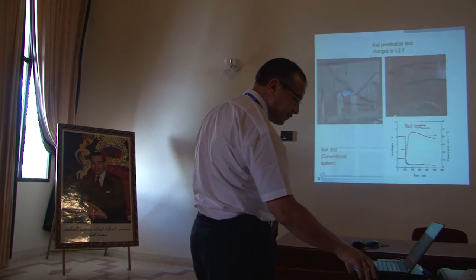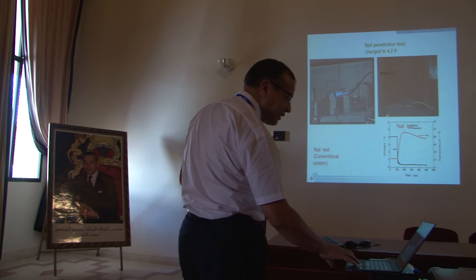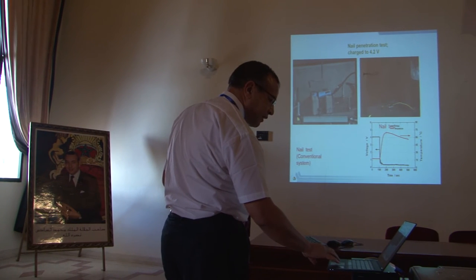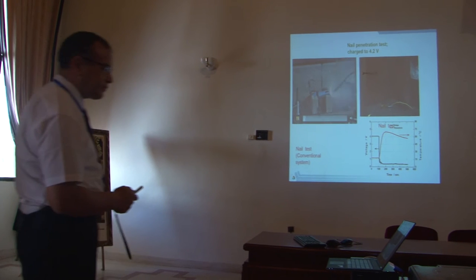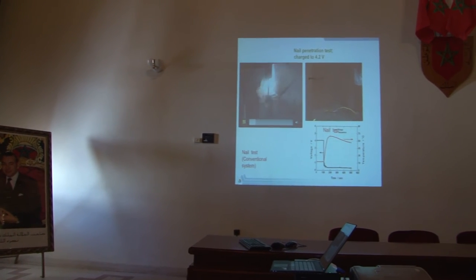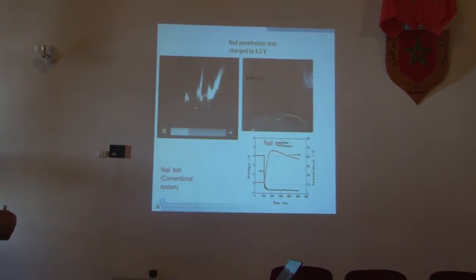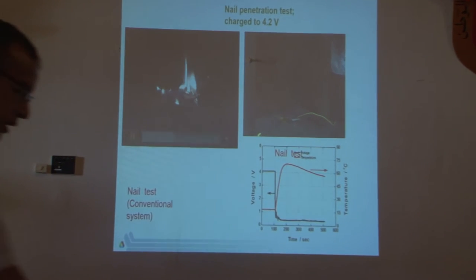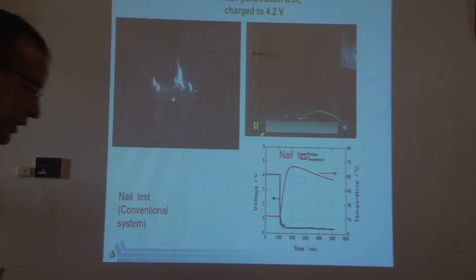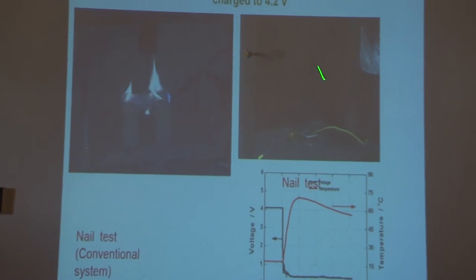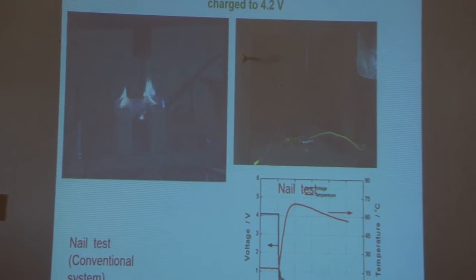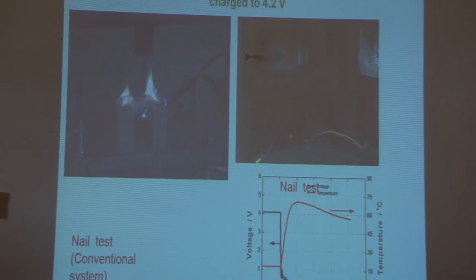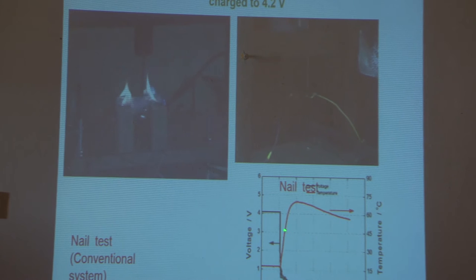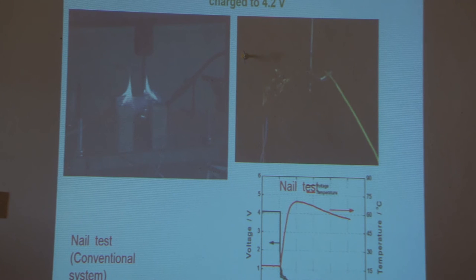And I think I have videos. I hope they can work. This is the NCA. I think it will work. We did a nail penetration. So what happened? The high nickel ratio is very, very unsafe, just because of the surface reactivity, because of the release of oxygen that reacts with the electrolyte. And that reactivity is very exothermic. You do it with the gradient material. I'm not sure you can see it there. There's a nail coming in. Nothing happened. And this is the profile of the temperature once you short your cell. You see the temperature went to only 75 degrees C. In this case, it's 500 degrees C, for instance.